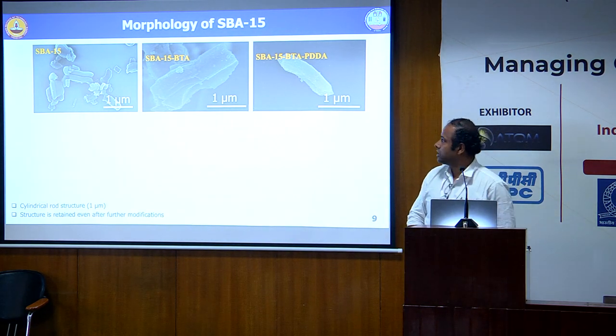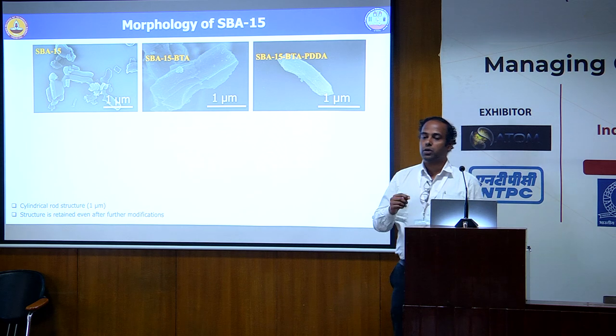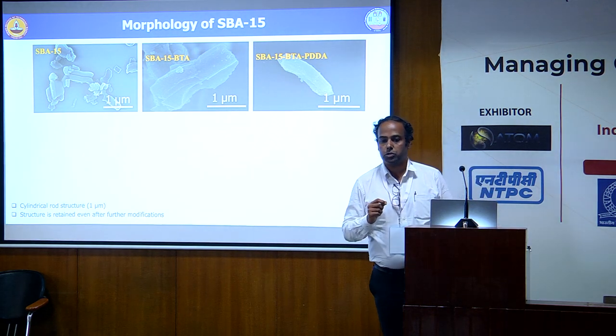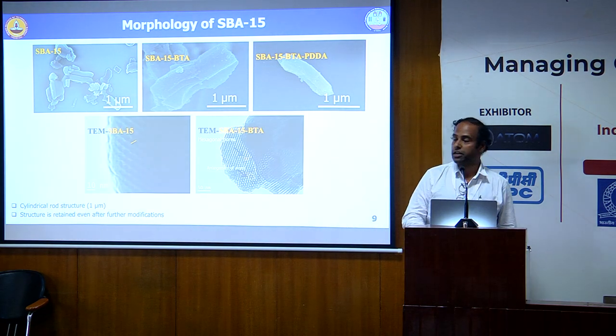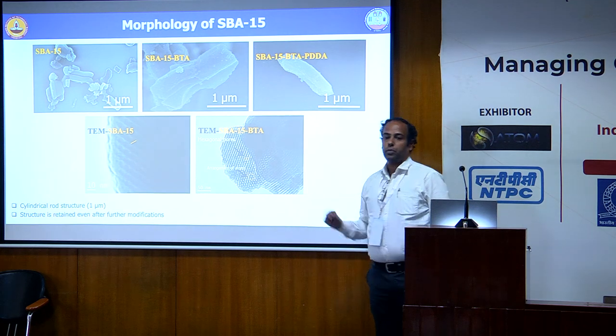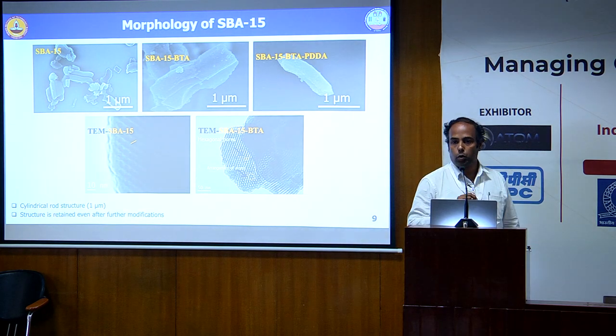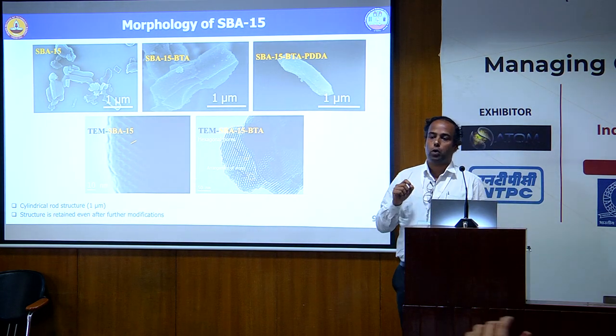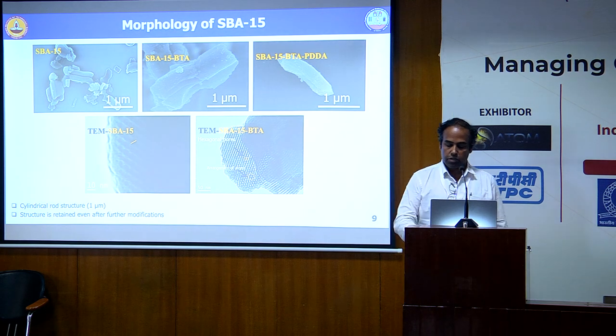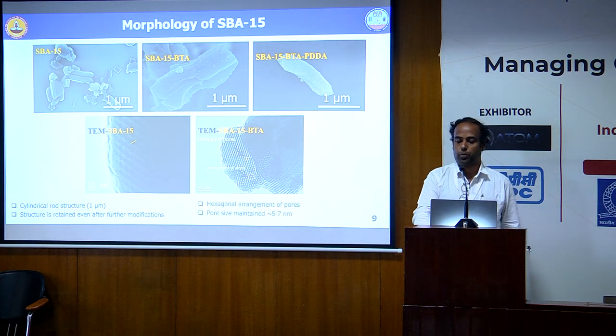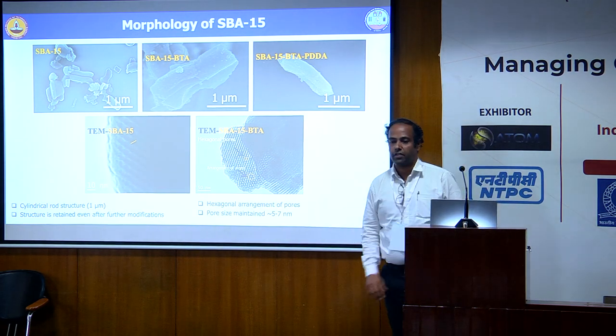And then we covered the benzotriazole with a polymer, which is actually in action when the pH goes towards 11. So after that, we see that it's more or less the same. So why mesoporous material? You have a lot of pores which can occupy a large volume of inhibitors inside it. So this is your TEM image, which shows the pore dimensions are approximately 5 to 7 nanometers.